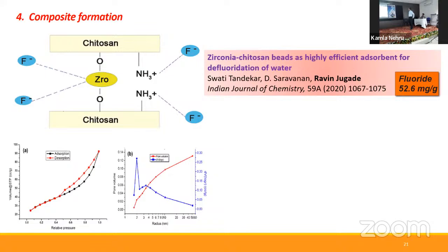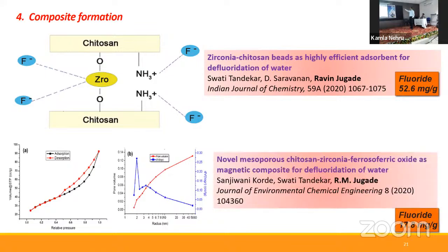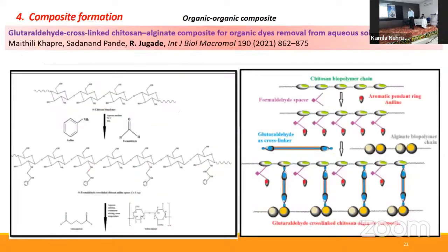Zirconia chitosan beads were formed and used for removal of fluoride from water. It has very good adsorption capacity, 52.6, one of the very good values reported in the literature for fluoride removal. Similarly, mesoporous chitosan, zirconia, ferrosoferric oxide, again a magnetic type of material, was used for fluoride removal.